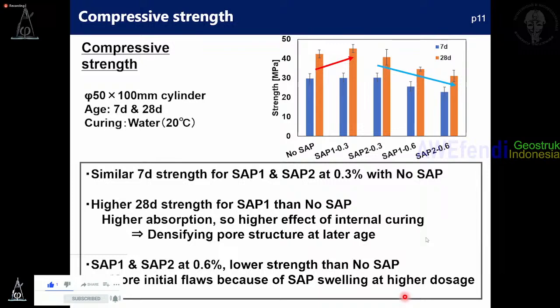And we test the compressive strength using the SHCC samples. You can see, compared with the no SAP case, we measured 7-day and 28-day strength. SAP 1 and SAP 2 at 0.3% got similar strength at 7 days, but even higher strength for SAP 1 at 28 days. But if you increase the SAP amount, the strength starts to decrease. So we think the higher 28-day strength for SAP 1 is because of the higher absorption, so it will release more water for internal curing at later age. That means a densification of the pore structure at later age. But because of the swelling of the SAPs, you have some initial flaws. So if you add too much, you will have a decrease of strength.